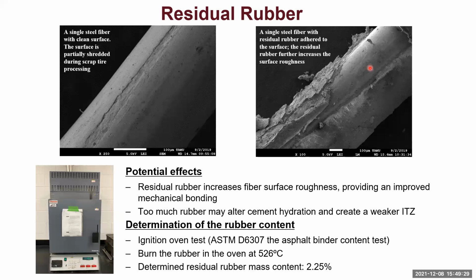So we determined the rubber content for our recycled steel fiber sample, and we found the residual rubber mass content was about 2.25%, which is very low compared to many other samples in the literature.